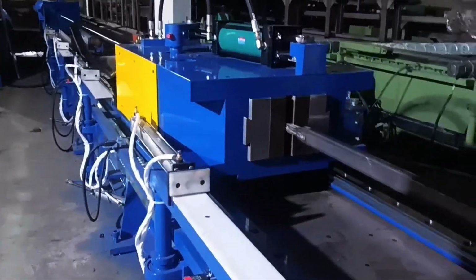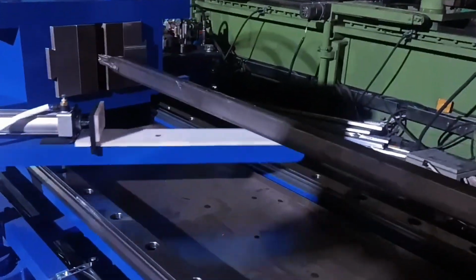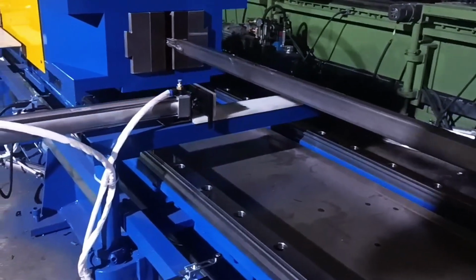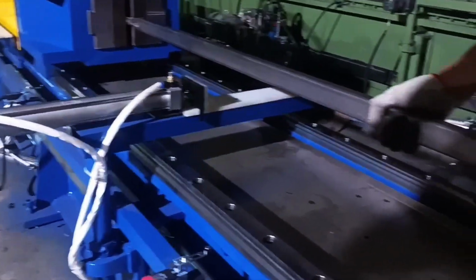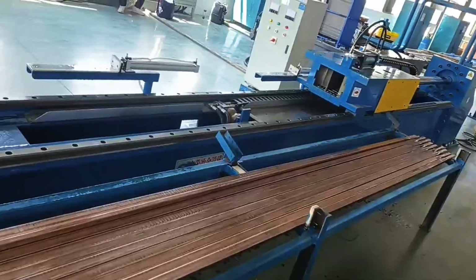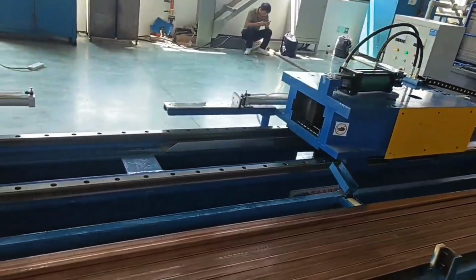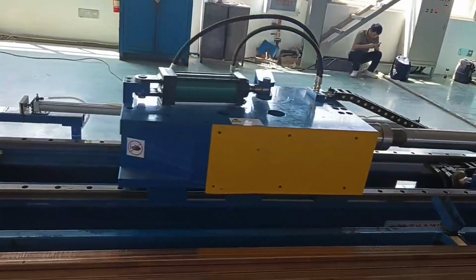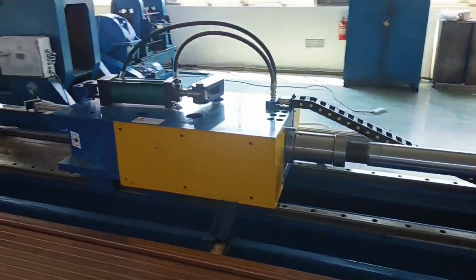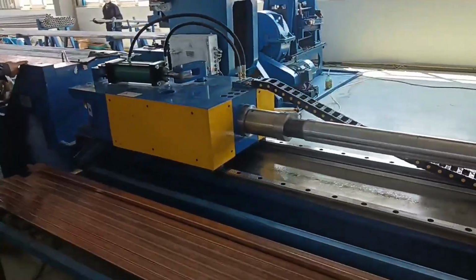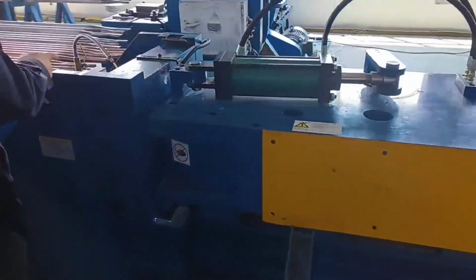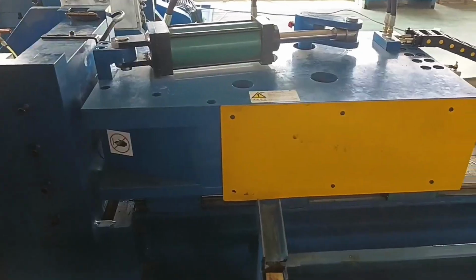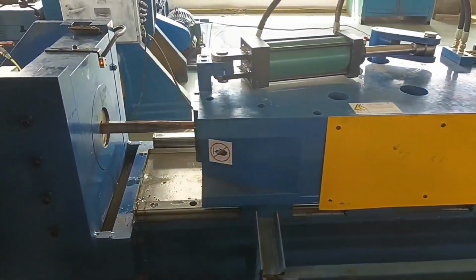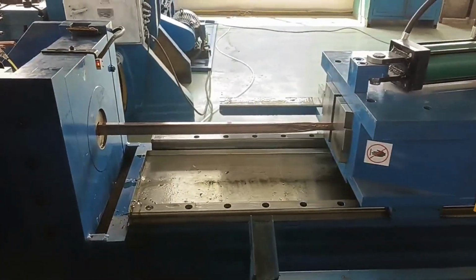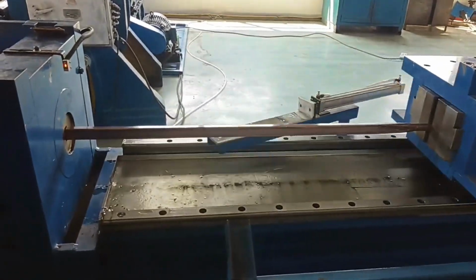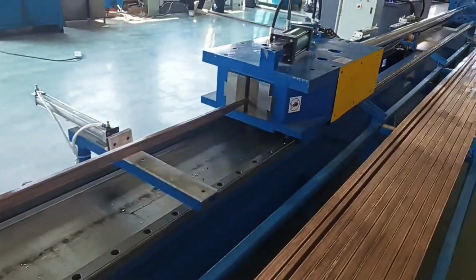Step-by-step operation. Loading tube or bar. Pointing the end, lubrication, powder or oil. Inserting through die. Gripping, drawing, unloading. Here is how you run a typical batch. Step 1. Roll a pre-straightened, annealed tube onto the feed rack. Step 2. Reduce the leading end on a pointing machine or swaging machine so it fits through the die. Step 3. Apply drawing lubricant, using a phosphate and soap coating or oil-based lubricant to reduce friction and prolong die life.